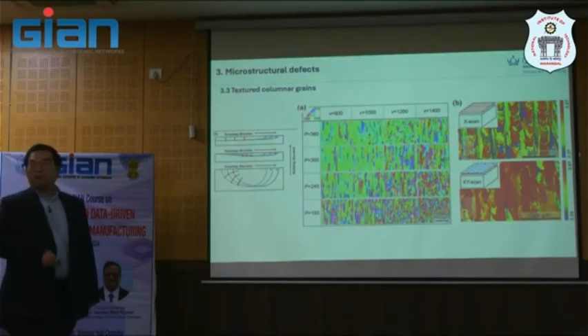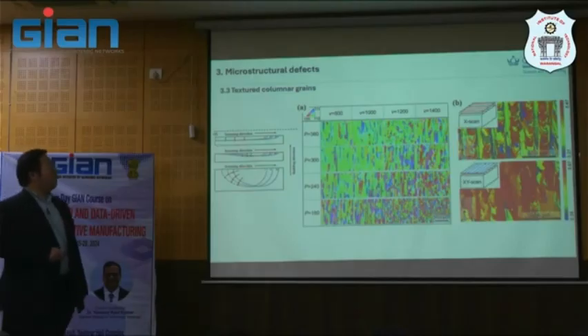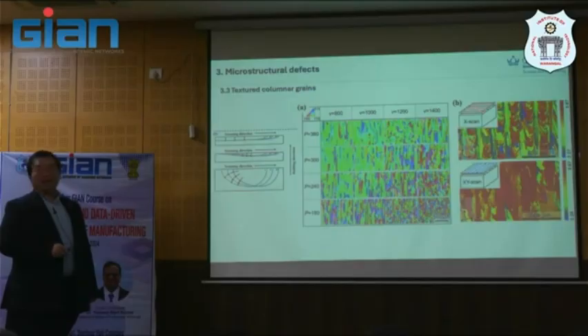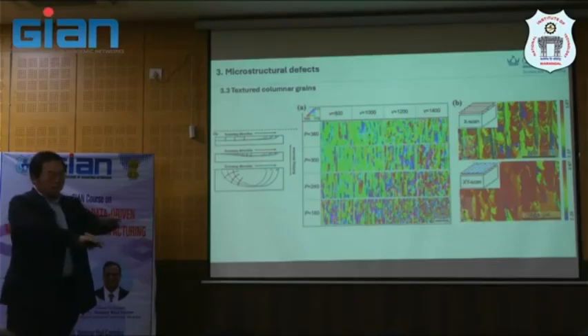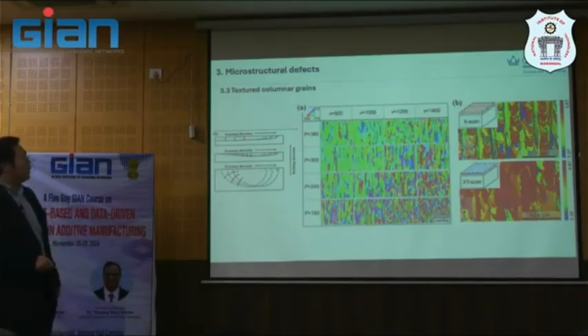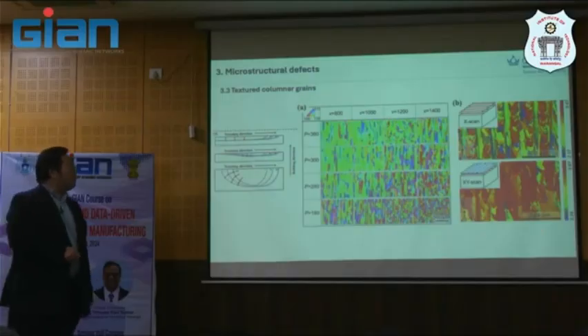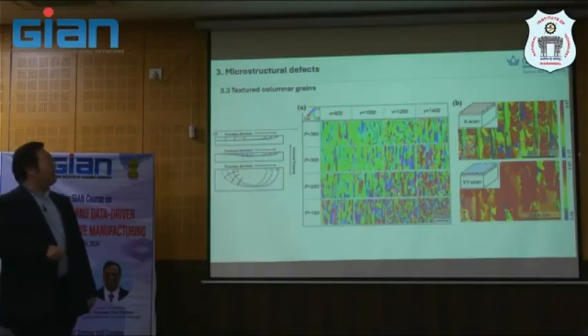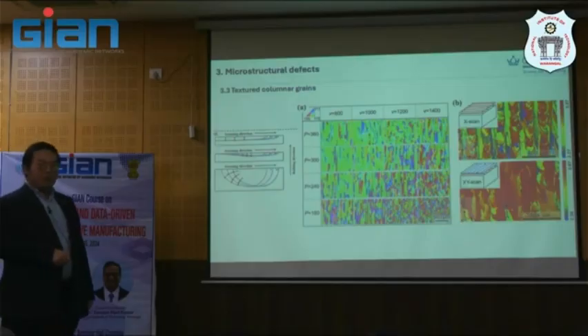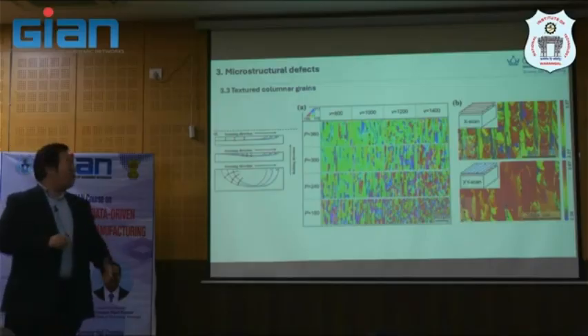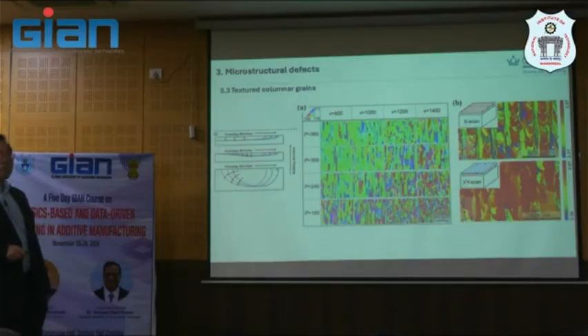You will see they are so different in microstructure. And this also contributes to the different scanning pattern that you use as well. If you use only X scan here, you get this microstructure. But if you use X and Y, alternated layer, X, Y, X, Y, this will lead to a different, more probably not preferable microstructure. We want more equiaxed, more small round-shaped microstructure that we need.